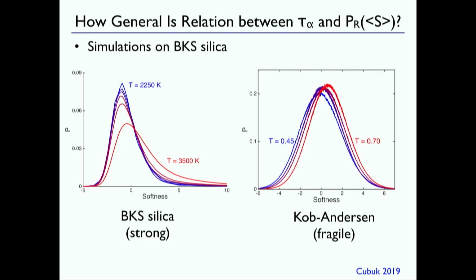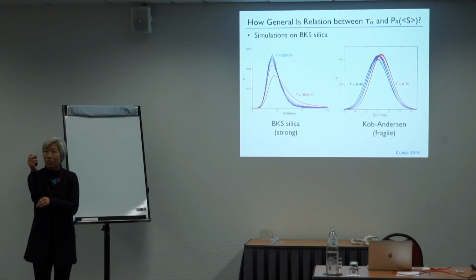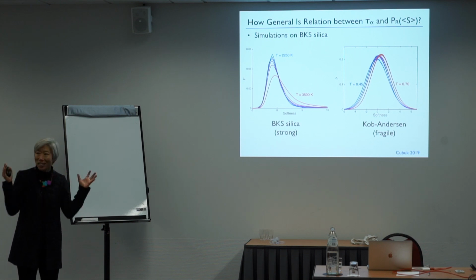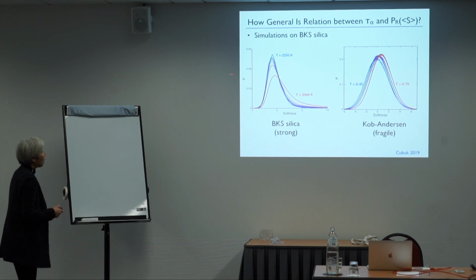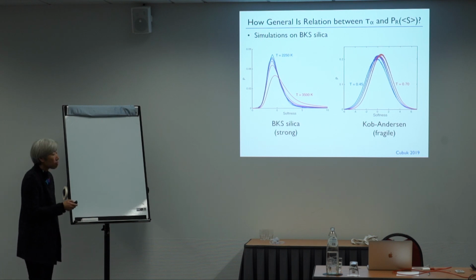Okay, how general is this? I showed you two systems, Lennard-Jones and the Weeks-Chandler-Andersen, which is just the repulsions. Okay, here's a totally different system. This is a model of silica, which is a network-forming covalently bonded glass. Totally different. Here I have a very different distribution of softnesses than for the Lennard-Jones case. This is what's called a strong glass former, so it's nearly Arrhenius. This is very super Arrhenius. But if I look at the probability for rearranging as a function of softness, it's still Arrhenius.